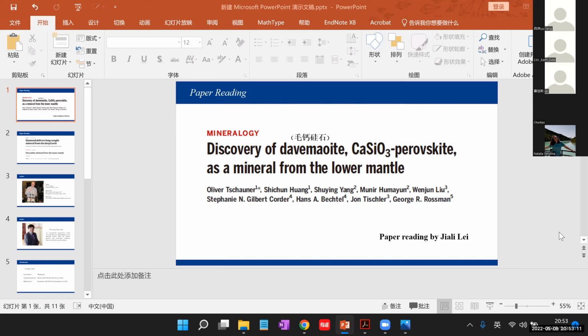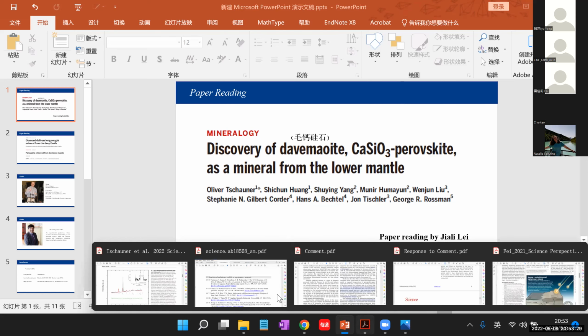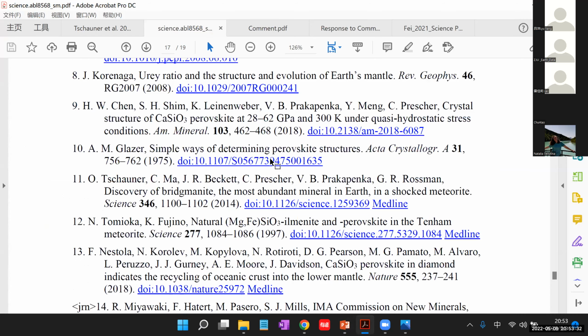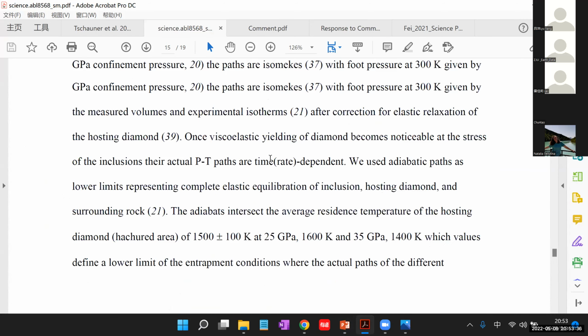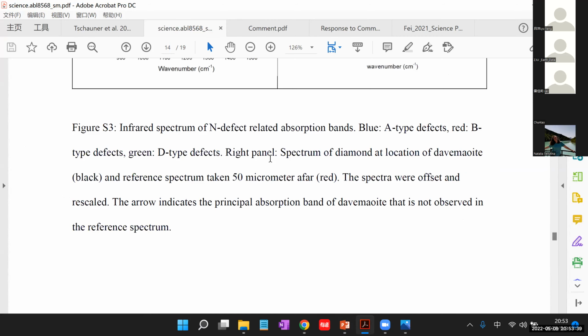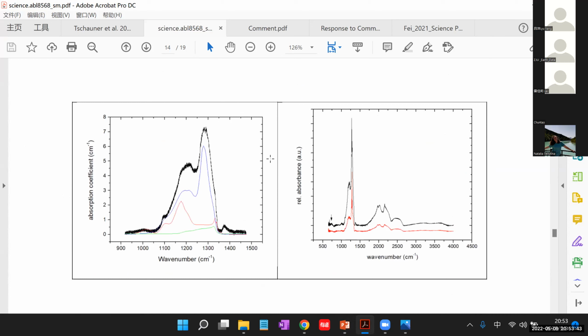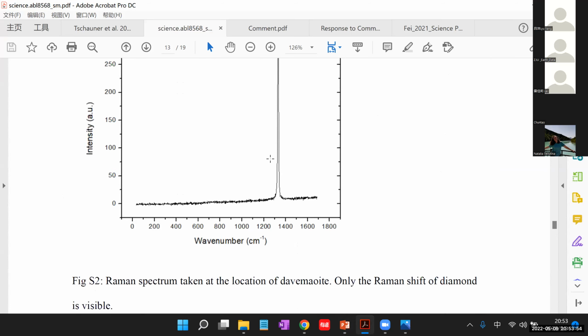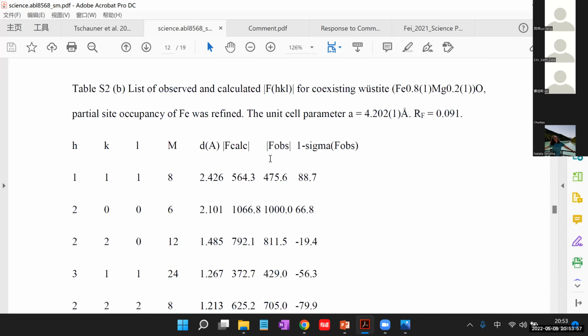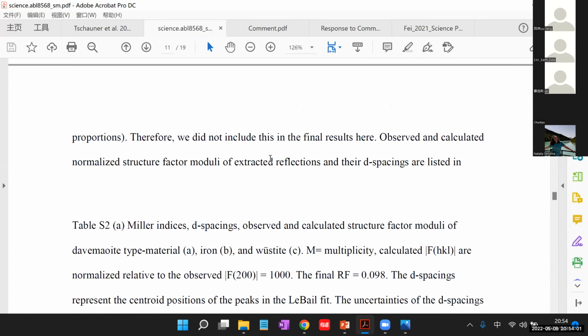So, Wumi, do you think those diamonds have a lot of trace elements? Diamond shouldn't have much trace element, but as we can see in the ICP-MS signal, only 2 peaks are visible clearly. Normally if the inclusion is big, the signals we get are a little flat. Like here we can see very sharp signals, like in figure 2. So the background is actually pretty low. In the diamond itself, the signal of the trace element is low and we can only see 2 sharp peaks. That indicates that those are signals of inclusion only. If the inclusions are big, generally the peaks are more rounded and spread.